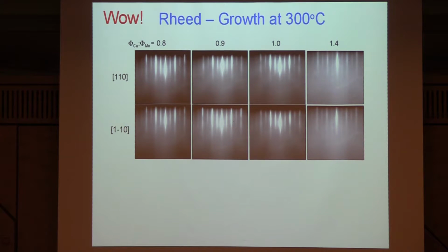Wow. Absolutely not. So this is the RHEED. These are the very first growths. These are the very, very first growths. So the guesses were really good. Growth at 300. And what this is basically showing us, for those who aren't familiar with looking at RHEED pictures, is that because they're nice and streaky, we have nice step flow two-dimensional growth. Okay, that's what we've got. Nice flowing steps, not big lumpy things. Okay. We've got fourfold symmetry, so not orthorhombic.